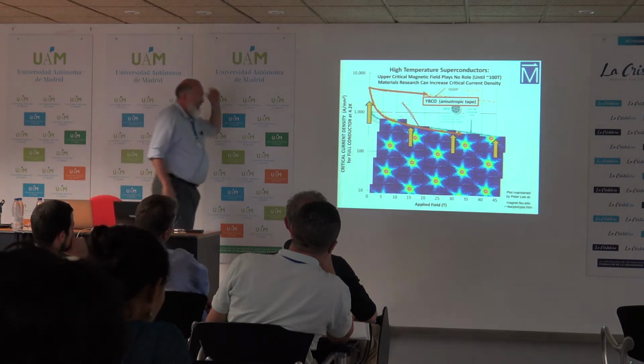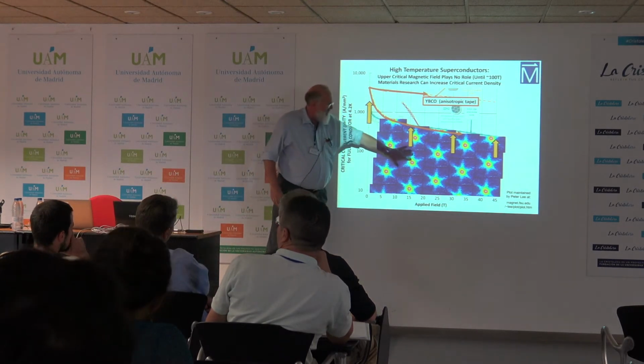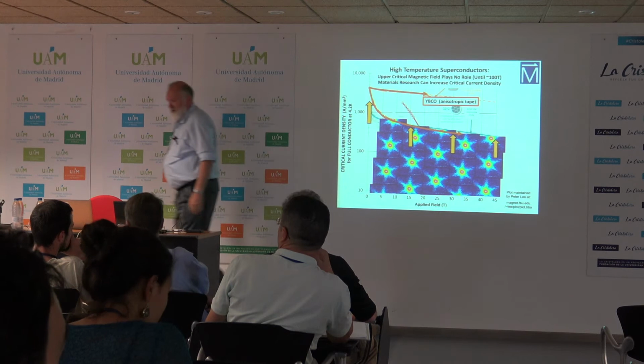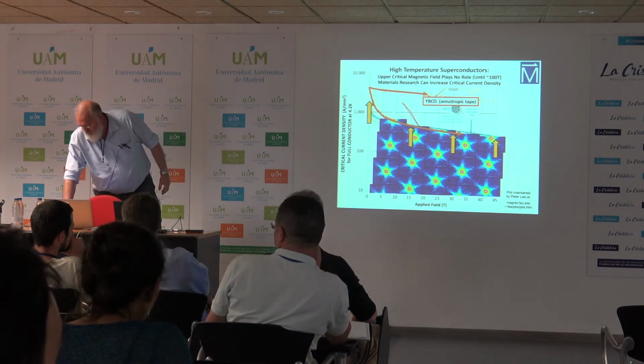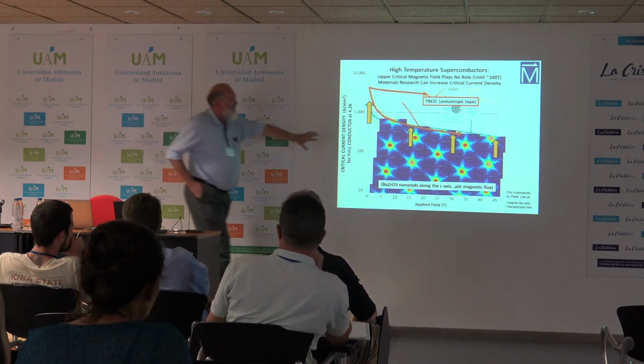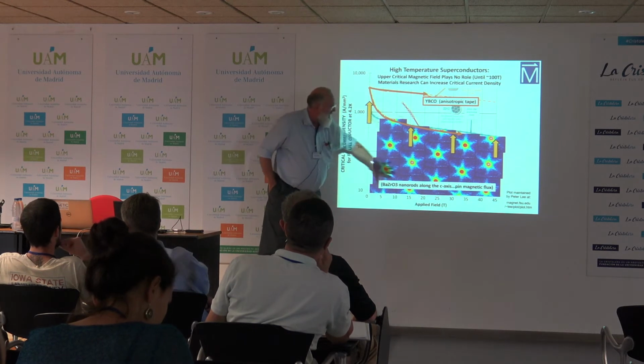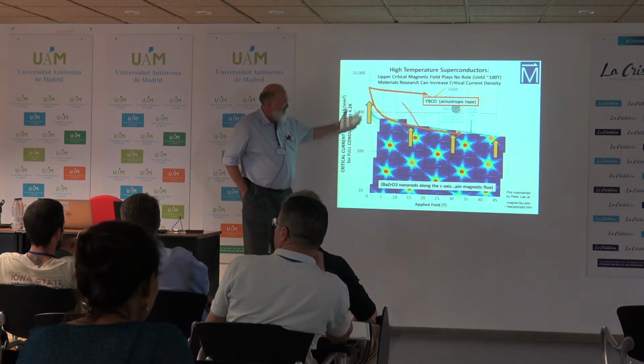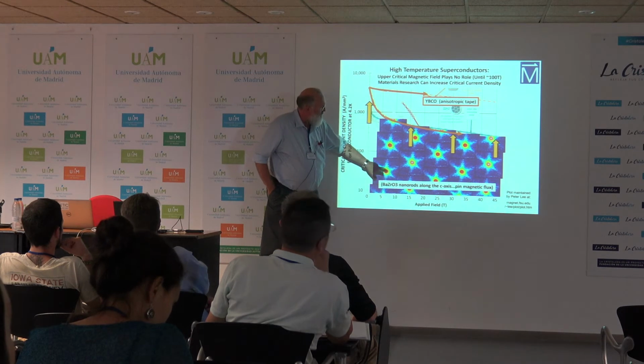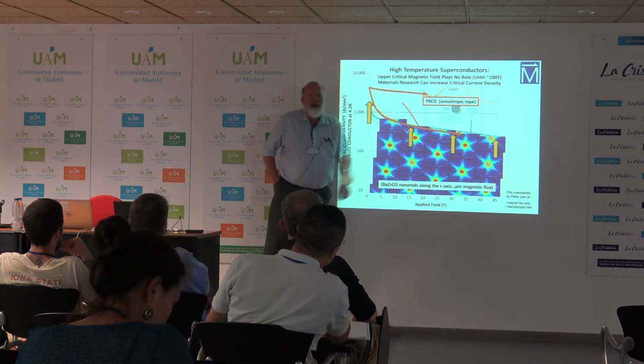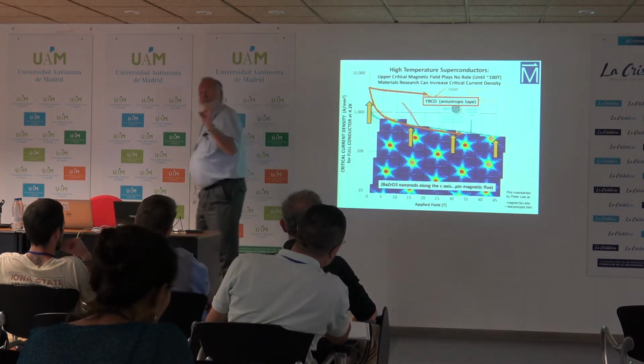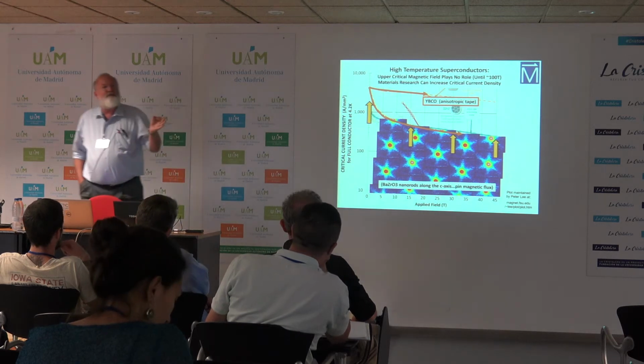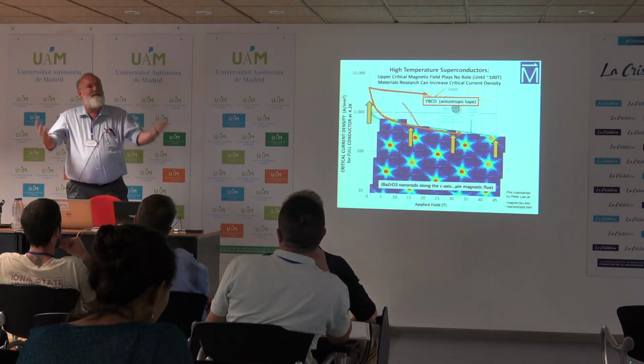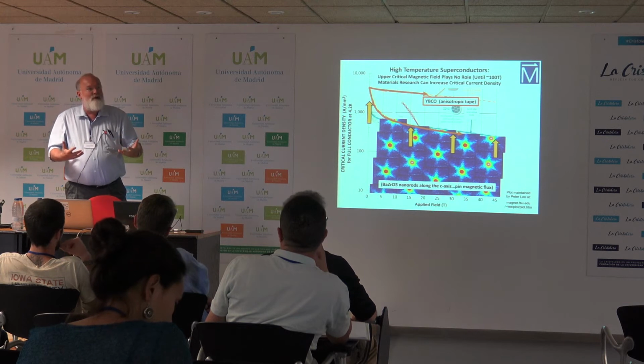So if we take Harold Hess's image of a single vortex and we make a perfect lattice out of it through the use of fake news, and then if you happen to have nanorods, I put them in exactly a hexagonal array. Of course, that's not the way nature works, but these vortices will preferentially find where you've got a nanorod and not move. And the point is that if your vortices move, you get dissipation. And so the superconductivity goes away unless you're pinning the vortices.